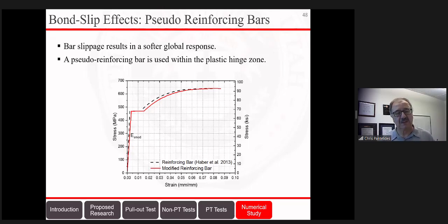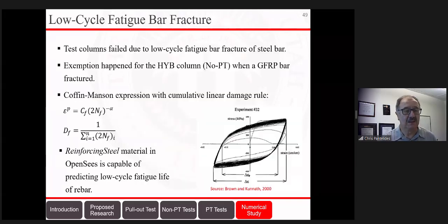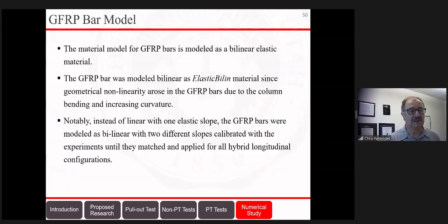And then for the steel, we have to be careful to model the slippage of the bars in the ducts, and we use a model by Haber 2013, which produces a pseudo-reinforcing bar like you see here. This is used to model the bars in the concrete. Low cycle fatigue is also modeled with the Coffin-Manson model, and we use the reinforcing steel material in OpenSees, which is capable of doing this.